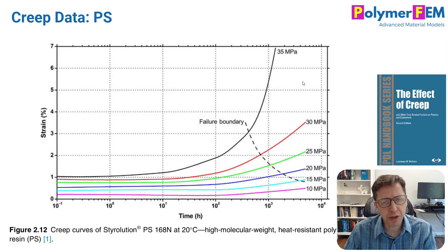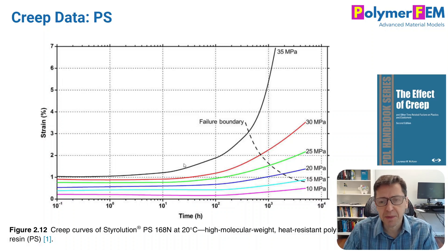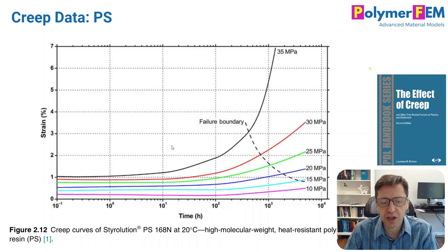Before getting into predictions, let's look at experimental behavior. I have creep data for polystyrene — different fixed stress levels in uniaxial tension — showing creep strain as a function of time on a logarithmic time scale. The first observation is that creep strain increases with stress, but the curves are not the same shape across stress levels.